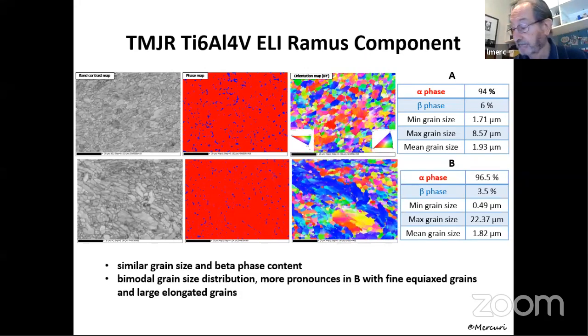What electron backscatter diffraction does for us is allow us to look at the orientation of the crystals, okay? So this is the orientation of the crystals in specimen A. You can see the crystal structure is very small here, okay? But this is the orientation of the crystals based on the Kikuchi pattern. I won't get into the complexities of that, but these are the crystals, and the way they're oriented, okay? And this is the orientation map. So this means whether a crystal is sideways, long, short, needle-like, or whatever. And if you look at the 2 different companies, this is an orientation that's pretty nice.